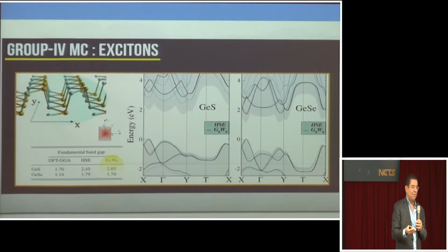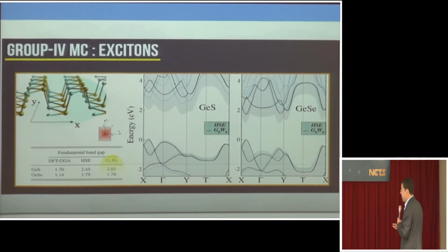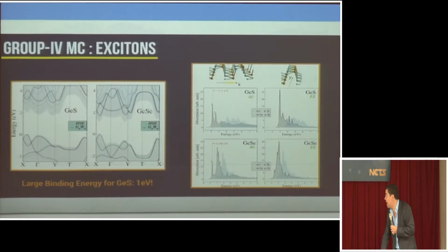So this lack of screening leads to an enhancement of the electron-electron interactions. So two-dimensional materials are naturally more strongly correlated than three-dimensional ones. And of course, one-dimensional materials are even more so. What I'm saying is that even for things like band gaps and excitonic states in these materials, you have to take this into account. If you want to understand electron-electron interactions, you really have to take them into account from the very beginning. And so this is an example of the absorption spectrum of different materials. You can see here this light gray is just DFT, and you see what happens when you do, say, something like GW. The shifts in spectral weight are very large.